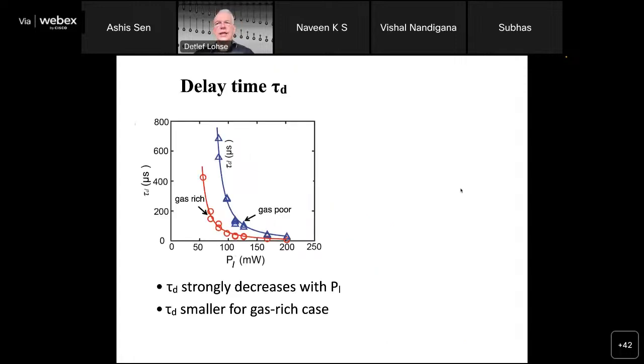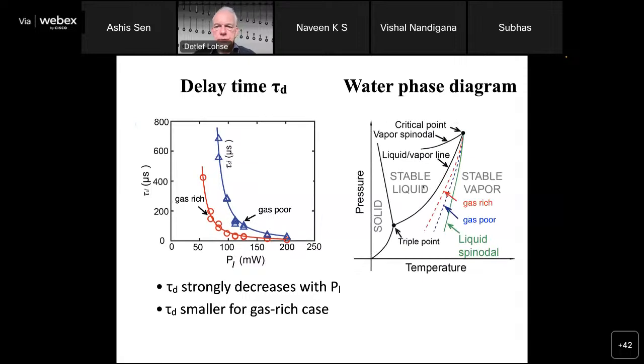And the key is the delay time. It is the delay time between turning on the laser and the nucleation of this bubble. You see that the delay time for the gas-poor case is much longer compared to the gas-rich case. And you also see that the delay time goes down with increasing laser power. The reason is that you go through a phase transition. In this phase space, you go from the stable liquid towards the vapor phase. And then here you're in this regime where you're superheated. If you're superheated strongly, at some point at this liquid spinodal curve, you clearly get nucleation of a vapor bubble, you can't avoid it. But in this regime in between, you can be superheated. And the question is, when does the superheated state go over to the bubbly state?